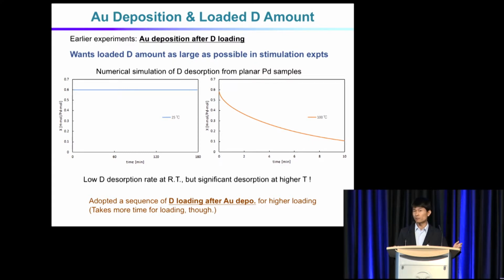As we investigated the diffusion or desorption of the deuterium out of the palladium plate, we found that even during the 10 or 15 minutes of our deposition procedure, a significant amount of desorption happens for deuterium out of the palladium. So we changed from Yamaguchi's procedure, because he deposited gold film after loading, but we switched the procedure so that we can sustain a sufficient amount of loading inside the palladium.